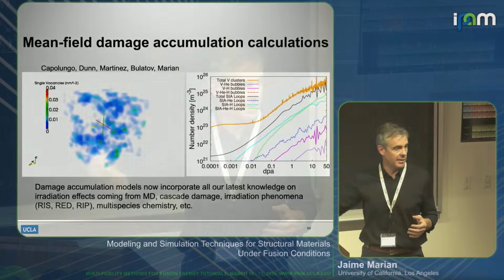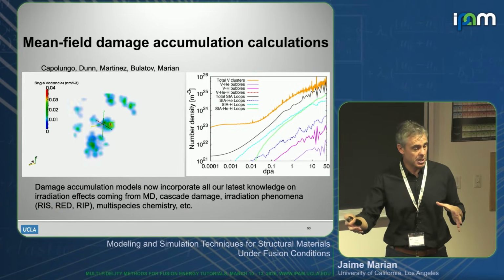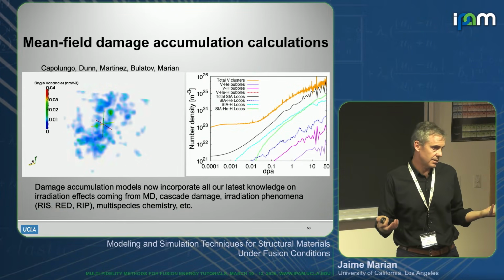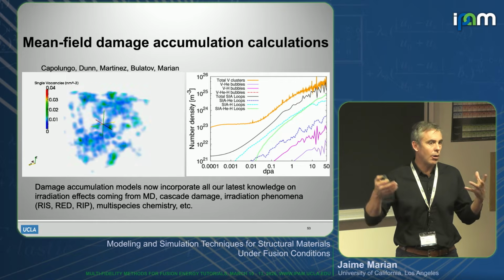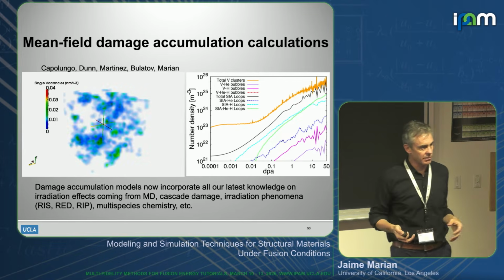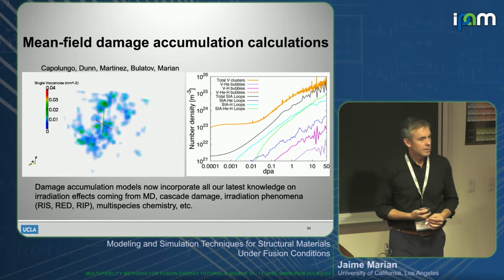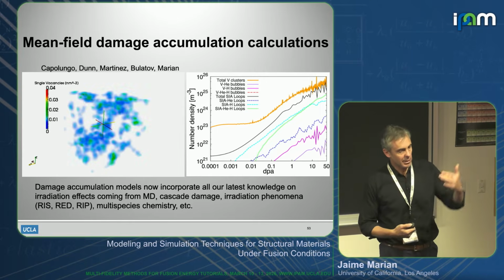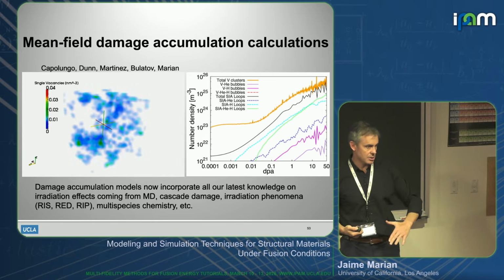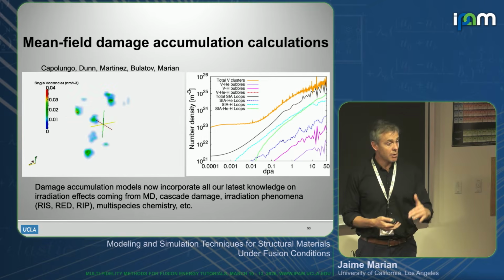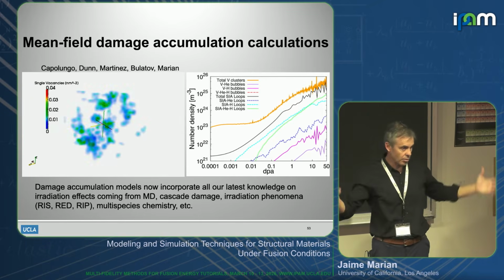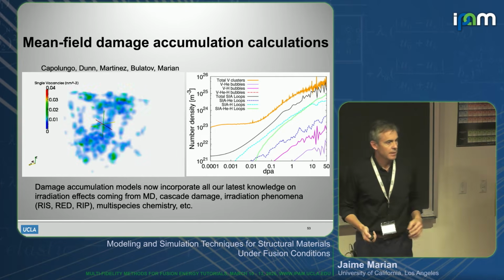Then we get that diffusivity, we put it in a kinetic Monte Carlo code, and then we see how, when those defects are produced, we can expect what the final outcome of the collective diffusivity of those defects will be. Very cool. That's really like multi-fidelity. So you get the rates from your DFT simulation. Exactly. From the lower scale, higher resolution model. And we use it in the right way, which is for that, instead of simulating the whole thing, which we can do.